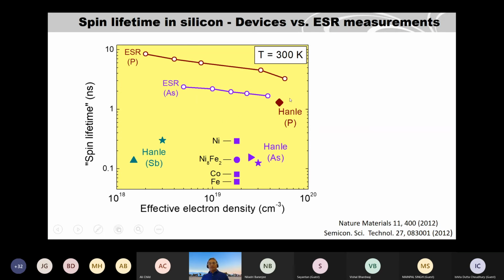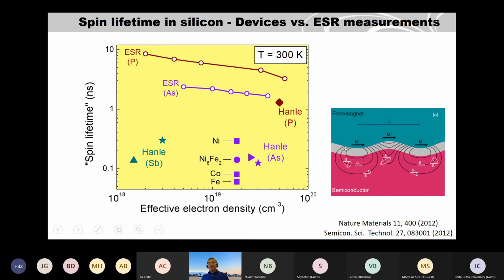But ESR experiments are done in a bulk sample, while we are dealing with a device here, and we have the interfaces with ferromagnets. For example, we have a semiconductor and a tunnel barrier. So it's a very ideal case here, but it has lots of pinholes and interface roughness. That interface roughness can create stray magnetic fields in these semiconductors. The stray magnetic field is also very inhomogeneous at different points here, and that can also reduce the spin lifetime. So you can find this in this review article.